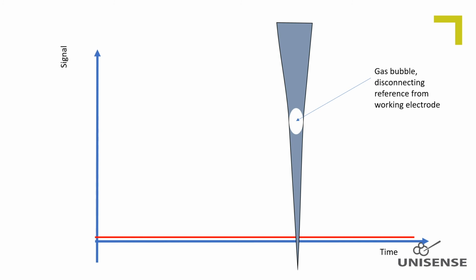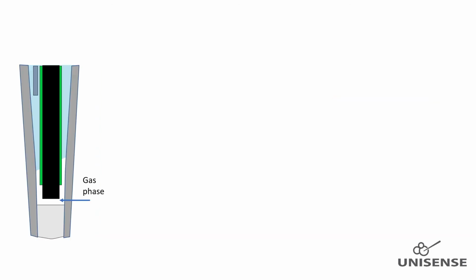There must be an air/gas phase in the electrolyte cavity in order to make room for temperature-induced expansions of the electrolyte. And if the sensor package is turned upside down during shipment, a gas bubble can be trapped in the tip. Such air bubble can be removed by shaking the sensor like it is demonstrated here. The bubble will become loose and rise to the top of the electrolyte cavity and the connection will be restored. In rare cases, a gas phase can evolve in the tip at the position of the working electrode, and such gas cannot be removed by shaking. So, if the sensor does not give any signal, this could potentially be the explanation.